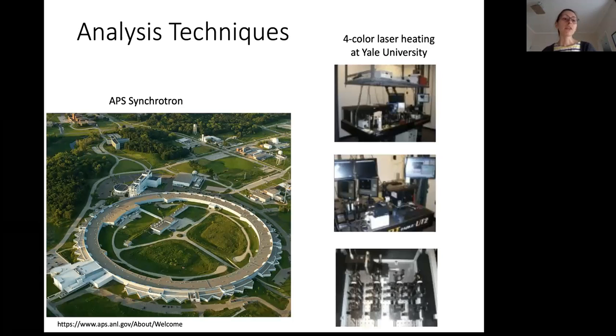Right, so we used several analysis techniques for these experiments. We did a lot of work at APS at Sector 16 and Sector 13, collecting diffraction patterns. And then we also worked using the four-color laser heating system that we had at Yale University, which worked by imaging the thermal emission of the sample while it was hot, which would give us a map of the temperature and some interesting observations about optical changes during heating.